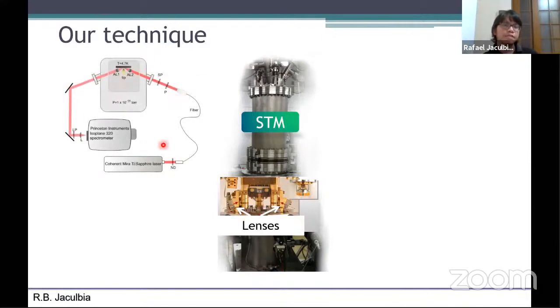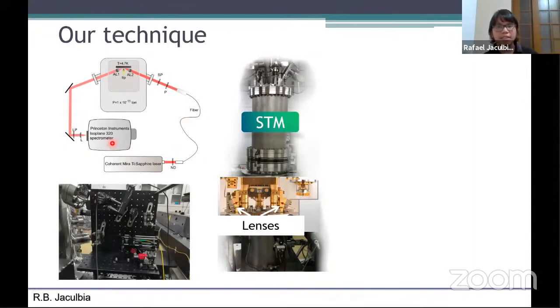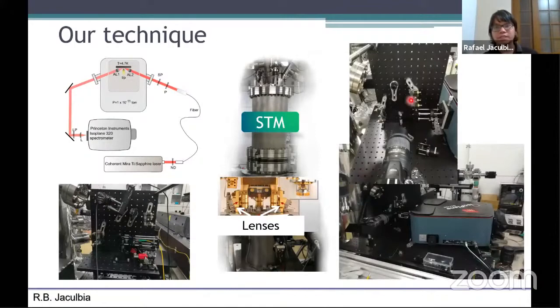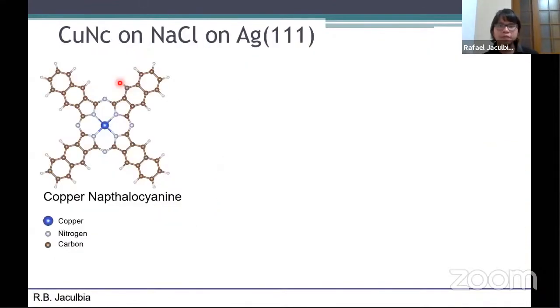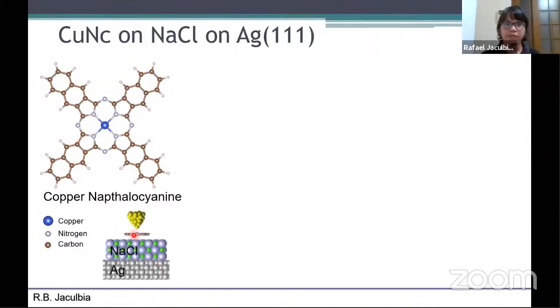So here is a schematic of the setup. We use a continuous wave tunable laser, and then basically just detect Raman. So in fact, there's nothing so special about this setup. We deliver the Raman signal to the STM via optical fiber, and then just detect it using conventional techniques. So we illuminate on one side and then detect on one side, and then approach the tip to that spot. And for our experiments, we use the copper naphthalocyanine molecule. In this case, we place the copper naphthalocyanine molecule on a sodium chloride surface, as I said. So just deposit the molecule on the sodium chloride supported by silver surface.